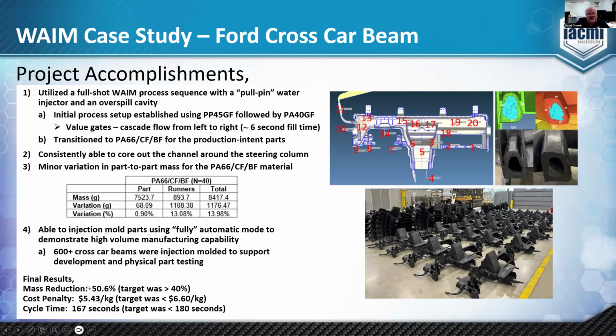The final results: we had a mass reduction, based upon this part mass, the highest of the spread, at 50.6%. Again, the target was to achieve greater than 40%. Our cost penalty came in at $5.43 per kilogram, less than our target. Our cycle time during the run at rate was 167 seconds. The target was to get less than 180 seconds. We subsequently followed up with additional molding trials, and we were able to achieve cycle times of 155 seconds.